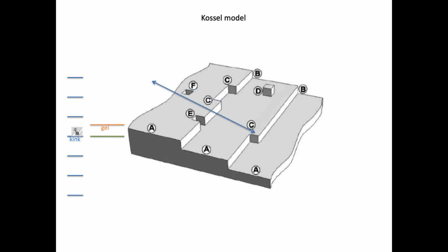However, if we get to the kink site, now we are lower in energy than the supersaturated state, so we're much less likely to come back out into the solution phase, and therefore the crystal is likely to grow quite successfully via the kink site.